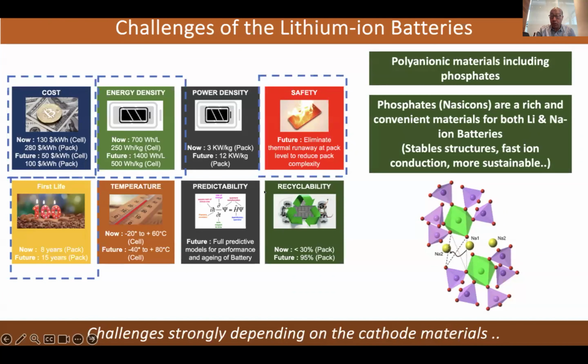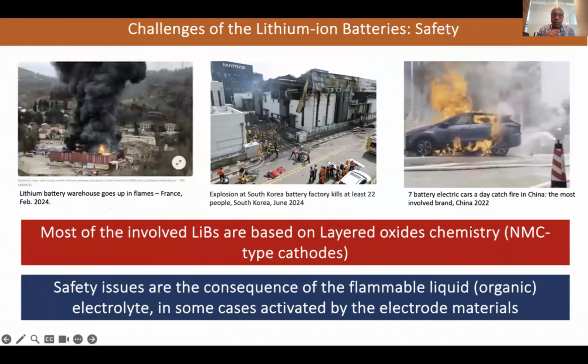For all these reasons, the polyanionic materials in general, including phosphate, are the good and perfect candidate to meet all these challenges. And phosphate, with this NASICON-type structure, from the atomic point of view, has a good crystalline feature. They are stable structures, so we can have many charge-discharge cycles for a long time, no problem. They have fast ion conduction for lithium or sodium, so we can have good power, fast charge, fast discharge, and so on. And they are more sustainable because phosphate comes from the earth, so no problem to use it and to put it back in the earth after using. That's why these are very important.